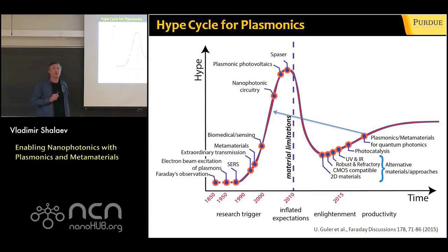First, it was misinterpreted. On the rough electrode, they said that's because the surface is larger, but the surface is not that much larger. So eventually they came up with a nice explanation, like Van Duyne, actually, yet another important person from Northwestern, Martin Moskovits. They said that actually it's largely because of very high local fields associated with excitation of surface plasmons in these nanostructures of metal. And because of this, you have dramatic enhancement in Raman scattering.